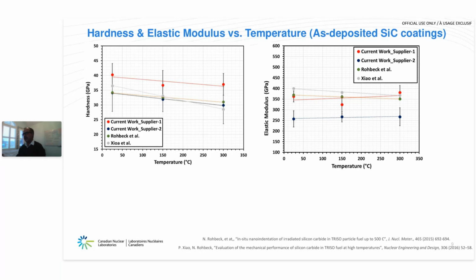these high hardness values. And as the temperature increased, the hardness did decrease with the increasing temperature, and it's consistent for both supplier 1 and supplier 2 TRISO particle silicon carbide coating. With the increase in temperature, the lattice resistance, which is very high at room temperature, drops, so that facilitates the dislocation motion, and the hardness does drop, and that's what we actually see. So our data here from two different suppliers agrees well with the literature values from 2 other independent investigations in the literature.